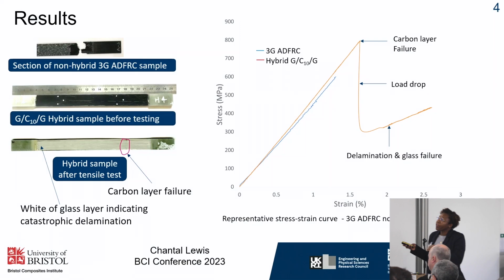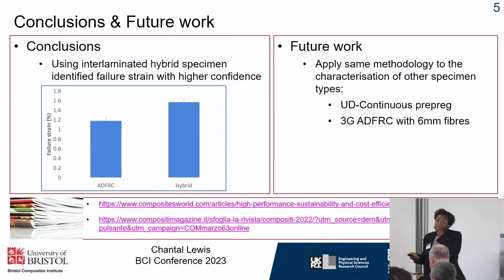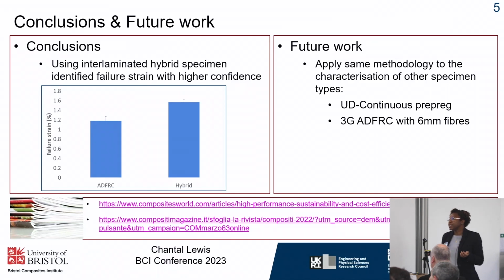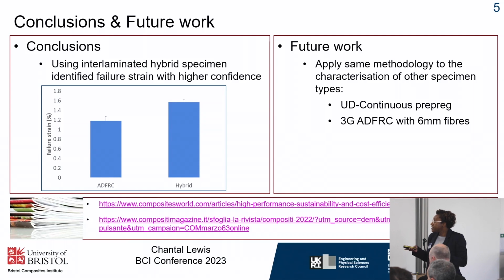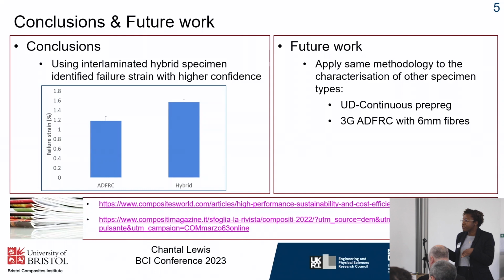Also comparing those results with the non-hybrid specimen, you can see there's a significant increase in the failure strain. So to conclude, it is possible to identify the failure strain of the carbon layer by using interlaminated hybrid specimens. And the hybrid specimen compared with the non-hybrid had an increase in the failure strain by up to about 35%.